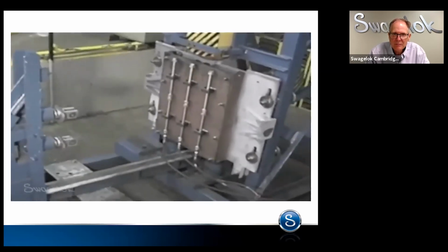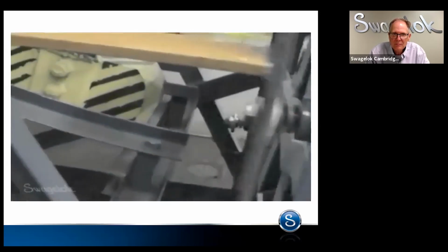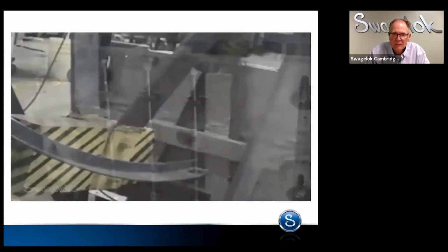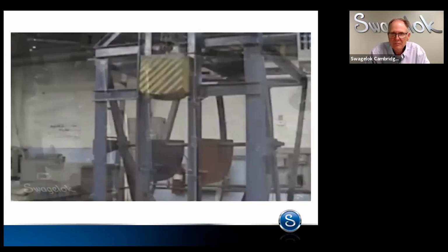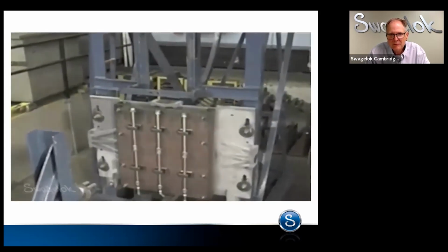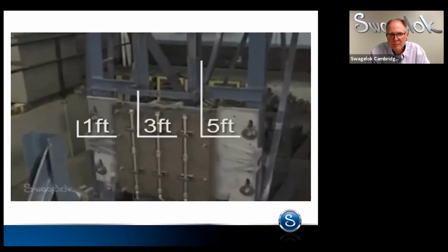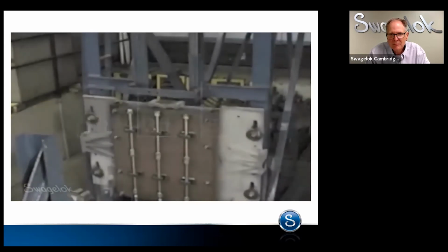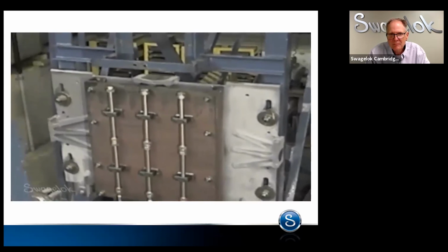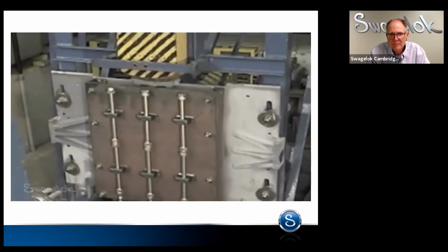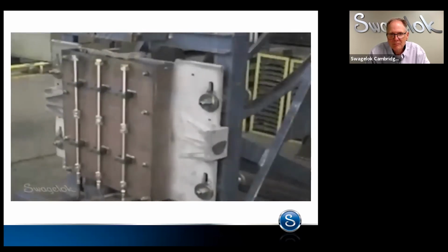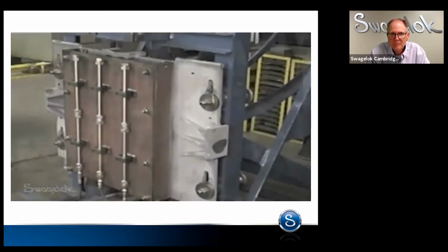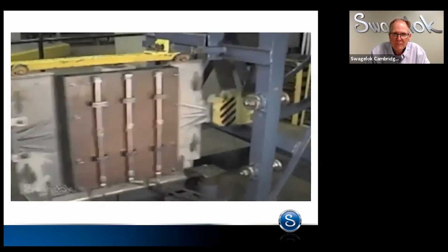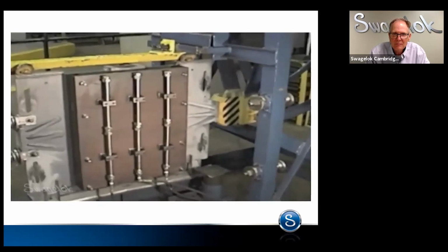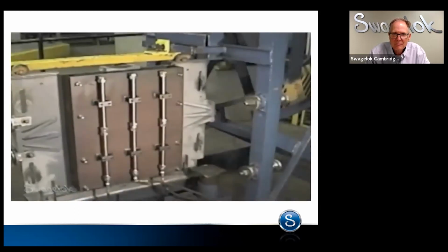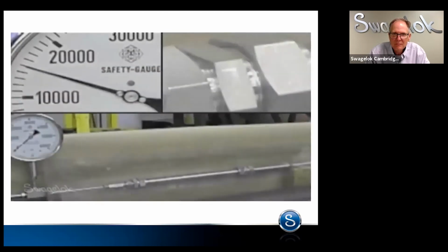Another third-party facility conducted a shock impact test on 1-inch stainless steel Swagelok tube fittings, also to ASTM F1387 requirements. The fittings were assembled and placed in a fixture. A 400-pound weighted hammer was dropped onto the assembly fixture from heights of 1, 3, and 5-foot elevations to simulate the effects of depth charges on submarines. The hammer drop sequence was repeated from multiple angles on the fitting assembly. This video details the amount of impact or side load the Swagelok tube fitting withstood, yet no leakage was detected during the pressure test after the impacts.